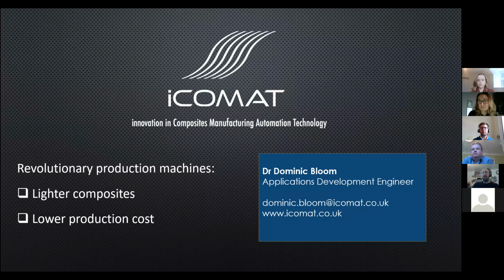Dominic, how does the deposition rates compare with competitor capability that probably can't do what you do? Yes, that's a good question. So during steering, we are much faster. So as I understand it, when an AFP machine has to steer around a tight radius, if it can be done, then it has to be done very slowly. So we are quite a bit faster. In a straight line at the moment, we're probably a bit behind in terms of linear speed, but there's no fundamental reason why we couldn't catch up. There's a fair deal of material optimization that can be done to get the parameters to allow us to travel a lot faster. I showed you that video we were working at 0.3 meters a second, but we've already done some trials which suggest that we can go a bit faster than that.